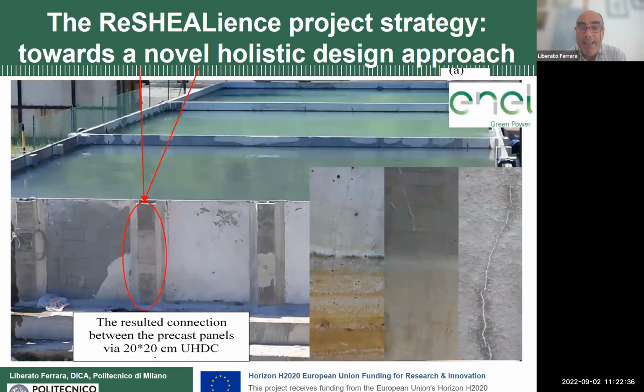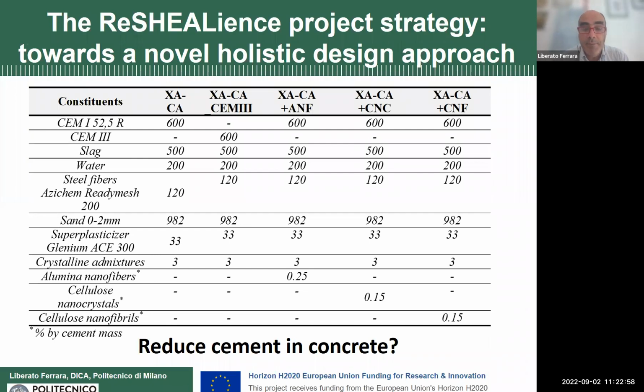But if I look at my structure and I consider that in ordinary concrete, I have 350 kilos per cubic meter of cement, but I have a 10 centimeter thickness, so I have 35 kilos of cement per square meter of slab. And I go to my UHPC solution where I only have 3 centimeters thick. Even if I have 600 kilos per cubic meter, with 3 centimeters thick, in the end, I only have 18 kilos of cement per square meter of wall in my structure.